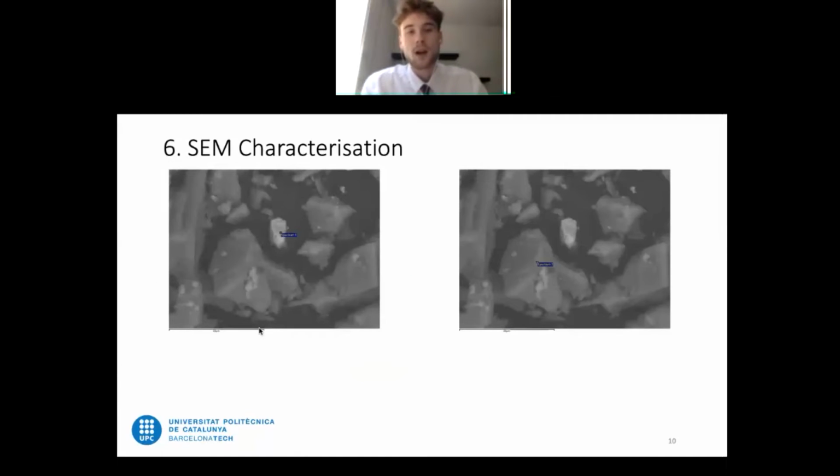So moving on to the characterization. Using the scanning electron microscope, we used 3 different types of detectors: detecting secondary electrons, backscattered electrons, and then X-rays as well. The secondary electrons allowed us to view the topography, but more importantly, the backscattered electrons allowed us to locate areas where reduction may have occurred. And here's the first backscattered image we can see.